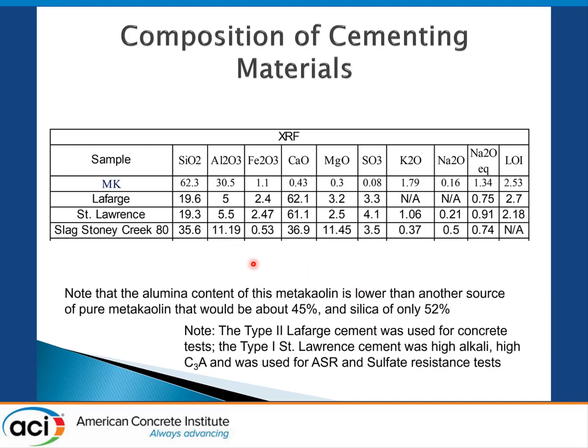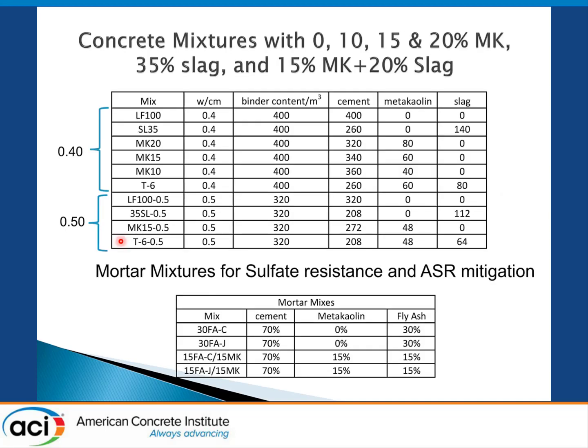So you can see the silica is higher because of the quartz impurities. And we tested a lot. We also tested ternary mixes with the slag cement from Ontario, because they were talking about bringing it to Ontario, and this was a commonly used SCM slag in Ontario. We did concretes at 0.40 water-binder ratio and a few mixes at 0.5. We looked at 35% slag, 10, 15, and 20% of this metakaolin, and a ternary mix of 20% slag and 15% metakaolin. We did our ASR and sulfate testing at 15 and 30% replacement.